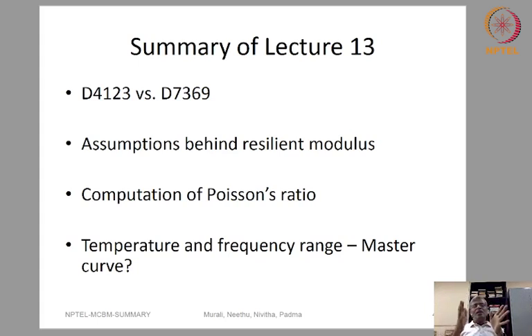Now there are limitations related to doing this test for a wide range of temperature and frequency. In our laboratory, we have not been able to do it at more than 35 degrees centigrade. Even at 35 degrees centigrade, the gauges will pop out. Then there are issues related to the gauge length, and issues related to the number of cycles to be used for reaching the steady state. These are some of the details that were given by Dr. Neetu Roy. In fact, some of you have even asked questions when these lectures were given: can we do it for cold mix, can we do it for different types of mixes? Now the answer to this question is yes and no.